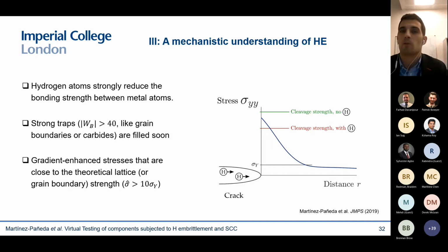showing you before, because we know that grain boundaries are actually quite strong. Maybe the grain boundary strength will be on the order of 10 times the yield stress. So in the absence of hydrogen, our stresses, even if you account for those dislocation hardening mechanisms, are not going to be high enough to reach the cleavage strength. So you will need this ductile fracture process. You will need those microvoid cracking mechanisms to see failure.